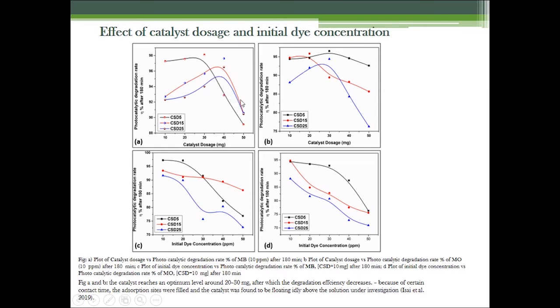It was noted that the degradation rate decreased significantly with the increase in the amount of the catalyst loading beyond 30 milligram, which may be because after certain contact time, the absorption sites were filled and the catalyst was found to be floating above the solution during the time of investigation.